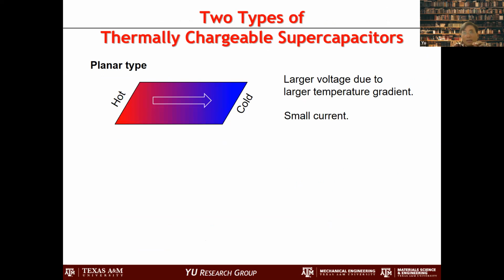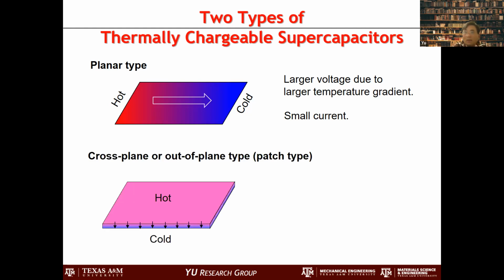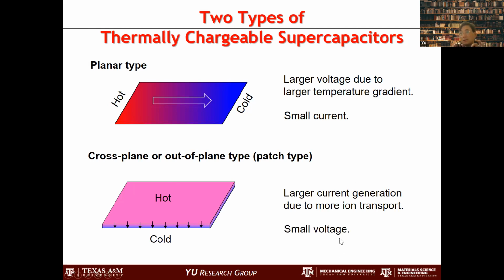So, the benefit here is that we can make a large temperature difference. But since it's very thin, what we can get in terms of current is pretty small, and that's the drawback. And same thing here, cross-plane or out-of-plane. So we can actually have a device in this configuration, and we can have a larger current, but the temperature difference is not that large. As you can see here, because it's thin, the voltage that we can develop is small. So you always have to pay the price, always pros and cons. There is a trade-off, and so we developed two different devices.